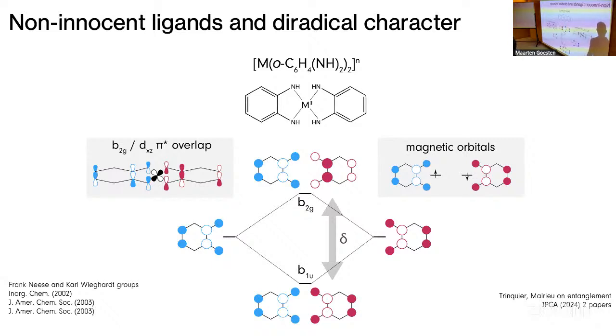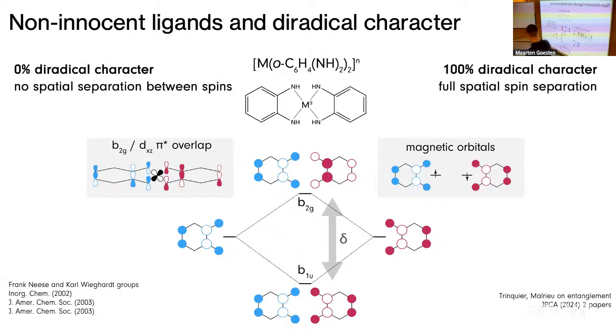But what density functional theory does is it produces a so-called broken symmetry wave function, broken symmetry solution. So it will put one spin predominantly on the right-hand side of the ligand, and the other spin on the left-hand side of the ligand. Group theory will tell you that this is not a proper solution to the Schrödinger equation, because such a wave function is not stabilized by all operations of the point group. Usually how we define it, if you have 0% diradical character, it means that none of that is happening. You get a perfectly antiferromagnetically coupled quantum state with the two electrons in this orbital. 100% diradical means full spatial spin separation.